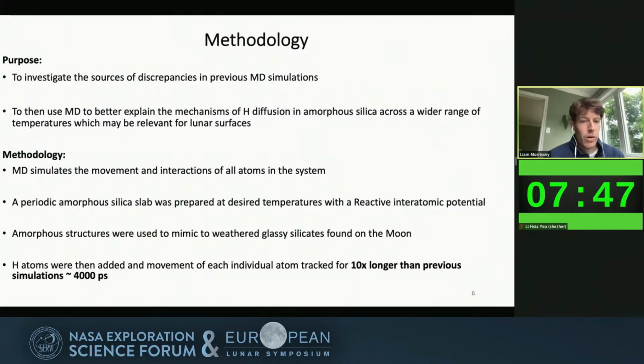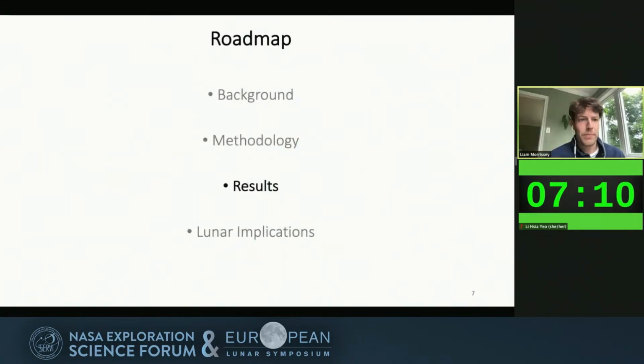Now, briefly, our methodology was that we used MD to simulate the movement and interactions of all atoms in the system by taking a periodic amorphous silica slab and preparing it to the desired temperature using a reactive interatomic potential. Now, we decided to use an amorphous structure because we wanted to mimic the weathered glassy silicates commonly found on the moon. After we developed our amorphous structure, we then added the H atoms and we tracked the individual movement of each atom for 10 times longer than previous studies. And that worked out to about 4,000 picoseconds. And I've bolded that because I'm going to talk about that later, but I want to just flag it for you. Now I'm going to move into our results.